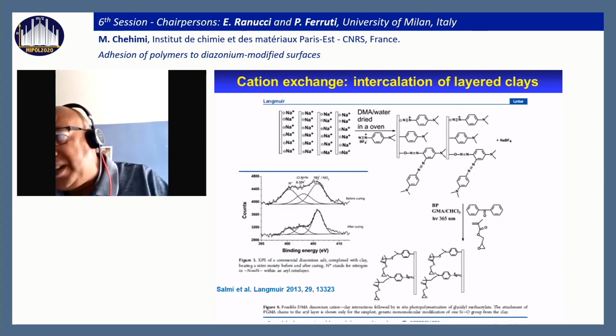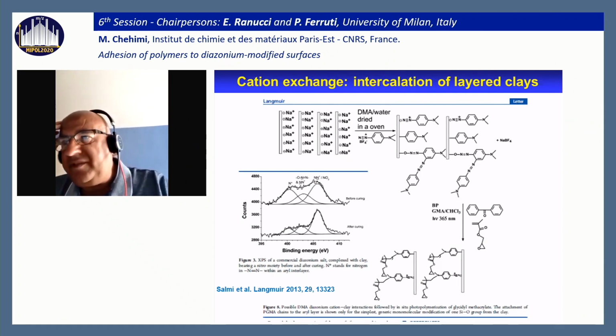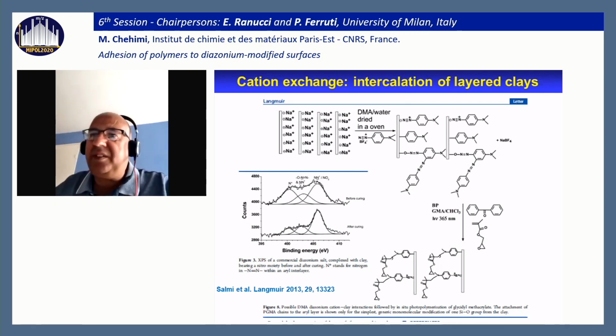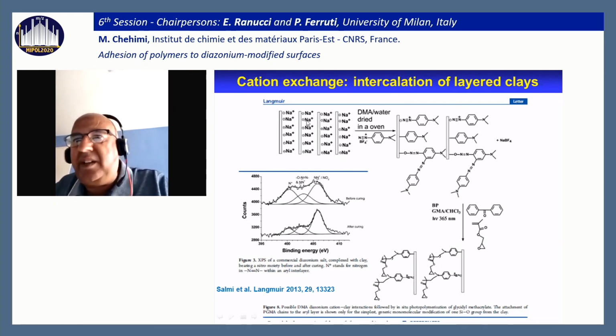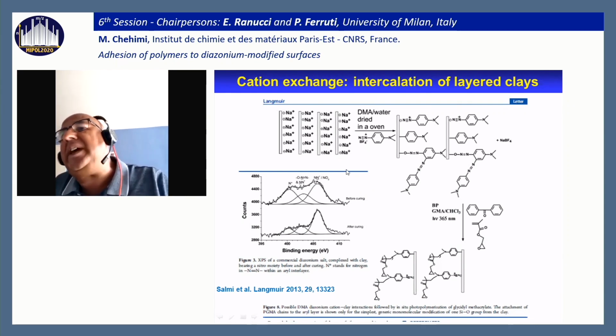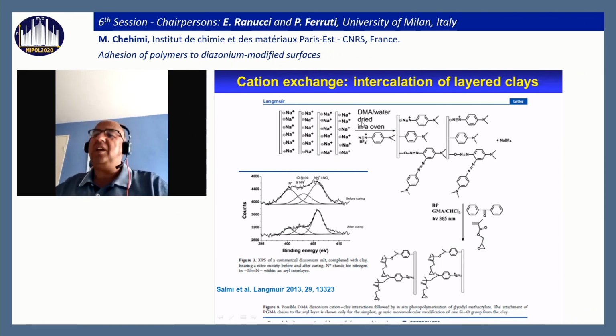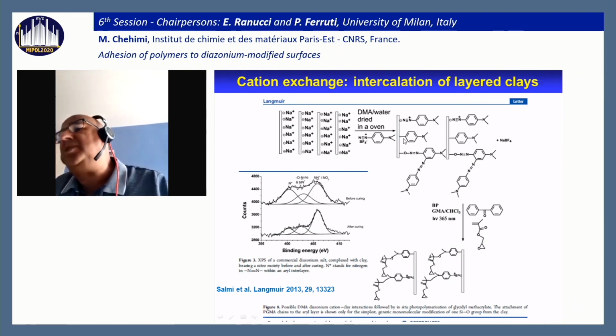With my group, we have demonstrated that there is a very immediate, instantaneous reaction of intercalation of clays with diazonium salts. For example, with sodium clay, the sodium is stripped from the clay, and it is replaced by the diazonium. If we heat up a little bit, we can make the reaction. We have a diazo-ether group, which is not very stable. So if we heat up a little bit, we can end up with an aluminosilicate-carbon bond at the interface.